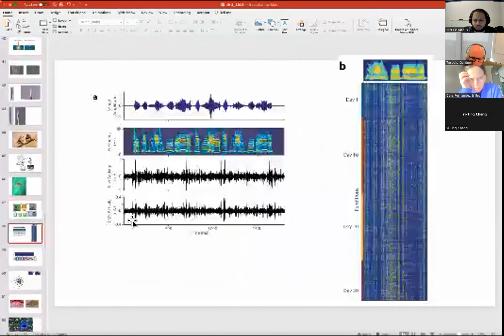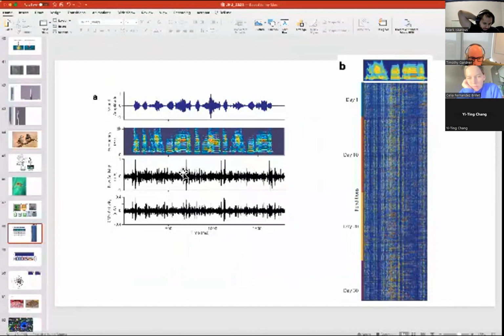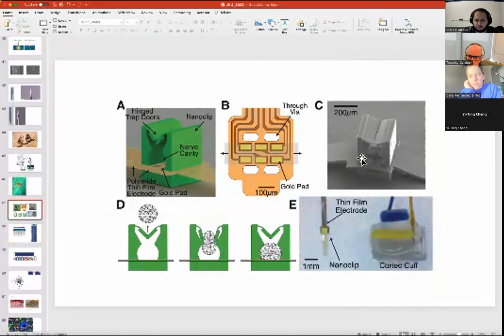And so we found with the really tiny nerve devices that, to our surprise, we got quite large signals. So signal-to-noise ratio was higher than anticipated for recordings outside the nerve, with signals up to close to a millivolt recording from the nerve. And one of the things that allowed us to use this effectively was having those 6 contacts with microfabricated structures.